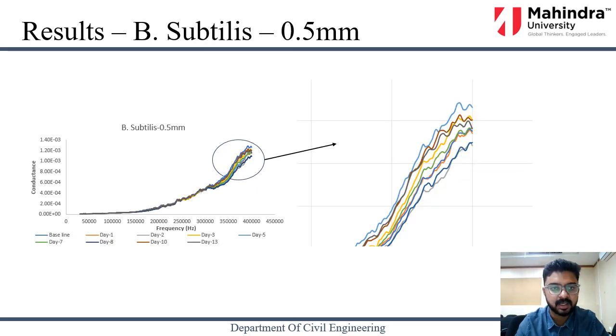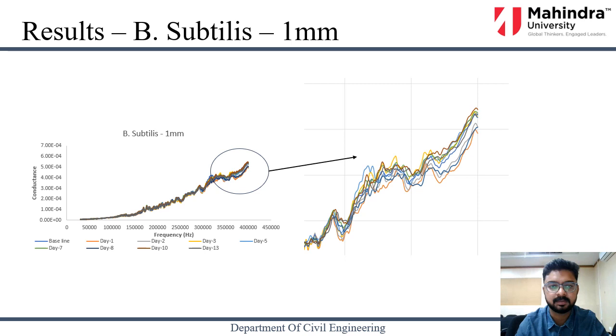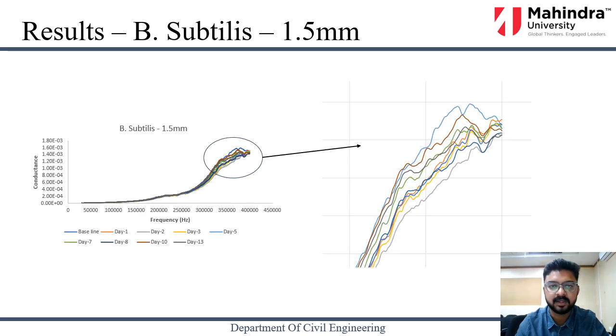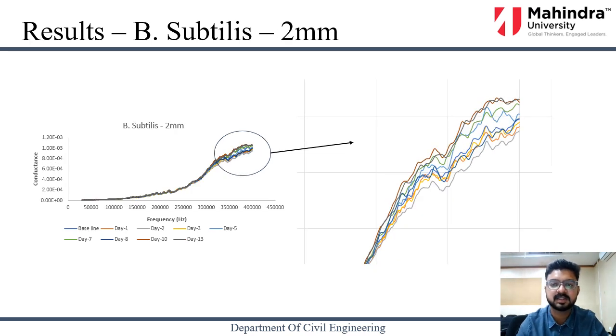So this is the 0.5 mm crack of Bacillus subtilis, and here also we can see there is some shift in the signature that we acquired, and this is the 1 mm subtilis, and this is a 1.5 mm crack which we induced with Bacillus subtilis, and as you can see there is some shift in the signature. So in all these signatures we can see there is some shift which says there is something happening inside, but we don't know whether it is because of the bacteria which we add or not. And we don't know how much amount of healing is happening inside the concrete.